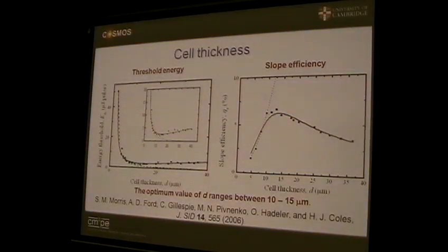So you need to carry out this kind of measurement. You make a simple wedge cell, and then look at the operating parameters of your device. Okay, you've got a combination of effects. If you have a long path length, you're going to get director fluctuations in your device, which lower the efficiency. If you make it too small, you don't have enough length to get gain and lasing. Okay, and again, you'll get a Beer-Lambert type of absorption at the surface. So you optimize the cell thickness for a given dye concentration, for a given material.